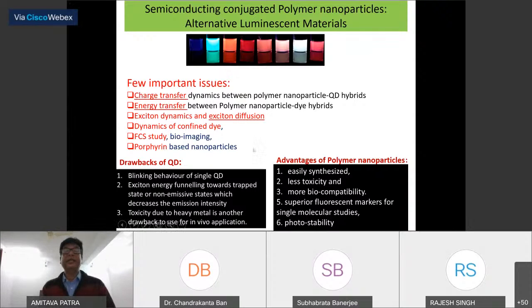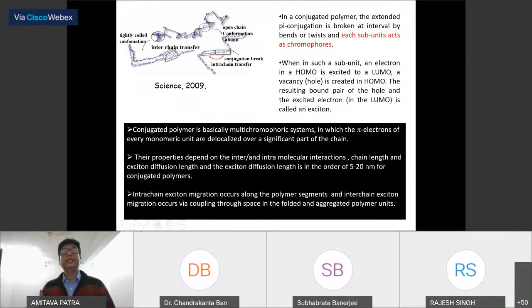You know the conjugated polymer, here you can tune the light from blue to red by tuning the length of the polymer, or if you dope some dye molecule inside the polymer nanoparticle, you can tune it. But these are the important issues we try to address: charge transfer, energy transfer, exciton dynamics, exciton diffusion. A lot of things. What is the drawback of the quantum dot, and what is the advantage of the polymer, because it is very useful for biological imaging purpose, so that there is no degradation. And polymer is conjugated polymer. Another advantage is that there is a pi conjugated system.